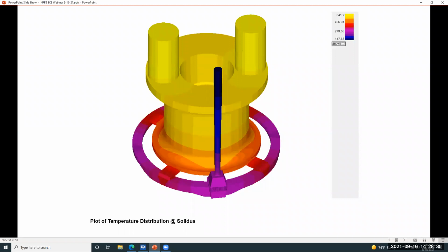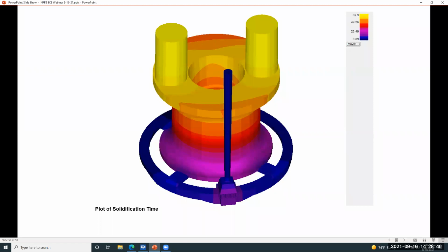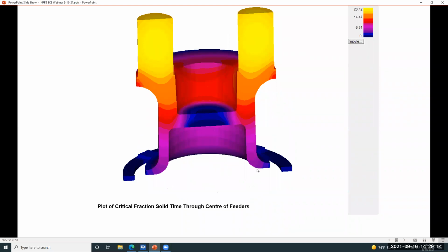If we look at solidification, this is a plot of the temperature distribution at the end of solidification. And this is a plot of solidification time. Generally speaking, we're looking for directional solidification, where we want to see different parts of the casting solidifying in a progression of darker to brighter. And we want to go out so that the last point to solidify is in the riser. That appears to be the case here. We can slice things through the middle and see, again, we're getting a good progression of color change through here, from the dark blue through the purples up into the reds. And our last point to solidify is in the riser.